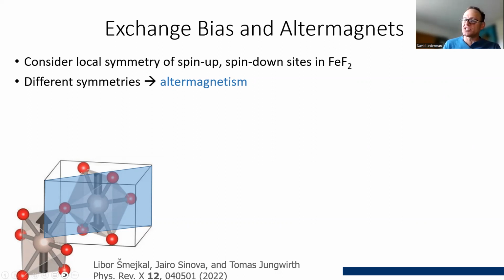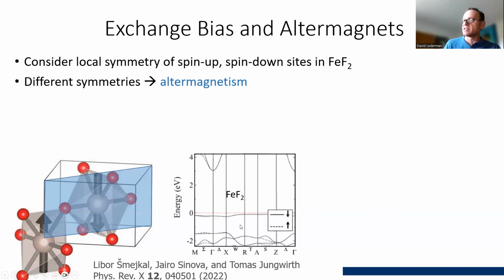And I think this applies to the exchange bias too, simply because one sublattice has a different symmetry than the other, and the exchange with the ferromagnet that would be on the surface here would be affected by the presence of these fluorines in a different configuration from one sublattice, right? The spin down sublattice versus the spin up sublattice like this.